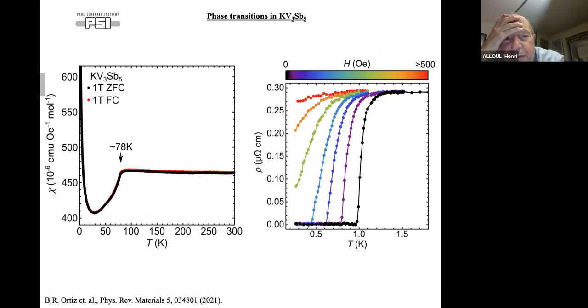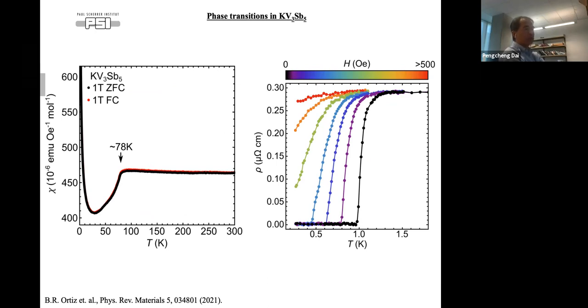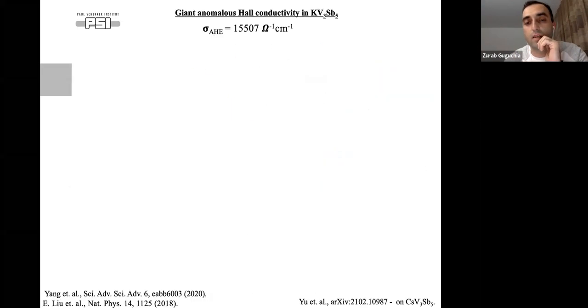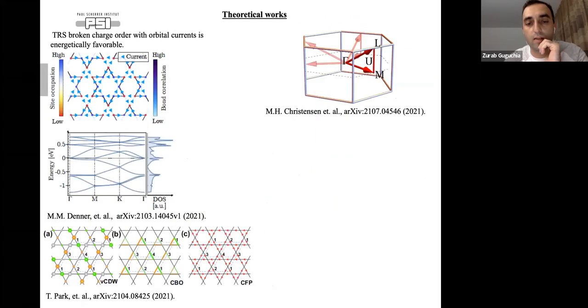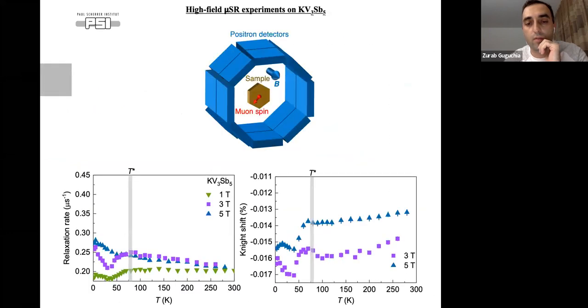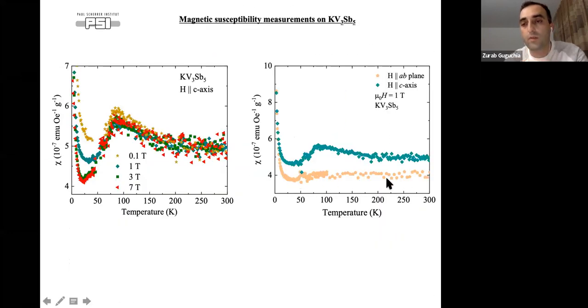Okay, good. So also, did you do a magnetic field experiment with the field in the plane and see what happens across the transition? Exactly. With the muSR setup we have on the instrument, because the crystals are very thin, I cannot rotate the magnetic field, and we also cannot mount many samples like this. So the only possibility I have applied is along the z-axis. But that's why we did susceptibility measurements in plane, and there we don't see any charge density wave anomaly. When we apply the field in plane, there is no change, while if you apply it out of plane there is. And I think according to Princeton, if they apply the field in plane, STM also does not see the change in intensities. It only sees it if you apply the field along the z-axis.